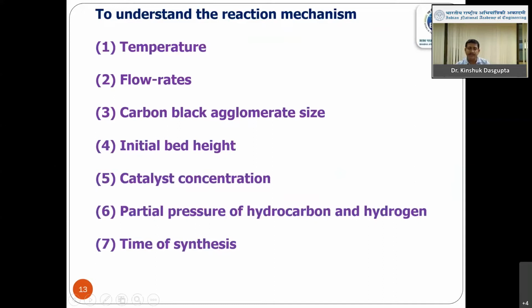Now, to understand what is happening inside the reactor, we need to carry out several experiments. So we varied different process parameters, and I am explaining why we varied. The first is the temperature. If we vary the temperature, we will come to know the activation energy of the process. If I get an idea of the activation energy, then I can estimate the rate controlling step. There are three possibilities in gas solid reaction. One is the external diffusion, that means the bulk diffusion. Then there can be diffusion through the pores, which is called internal diffusion, or there can be a chemical reaction. Now, if my activation energy is high, that means chemical reaction is dominant, that is rate controlling. But if my activation energy is low, typically below 10 or 15 kilojoule per mole, then we can consider diffusion control regime.